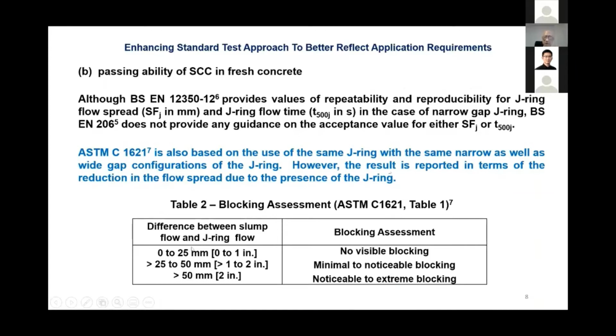So they use 25 mm difference in the flow diameter. That means the flow of the concrete is reduced by 25 mm from the standard slump flow. Then it's considered okay. Between 25 and 50, not too good. Over 50, definitely not acceptable. So that is a very good simple site practice. But for us, we can extend it a little bit more, by using the index, which I'm going to explain further, that will particularly give us a lot of other things we can do.